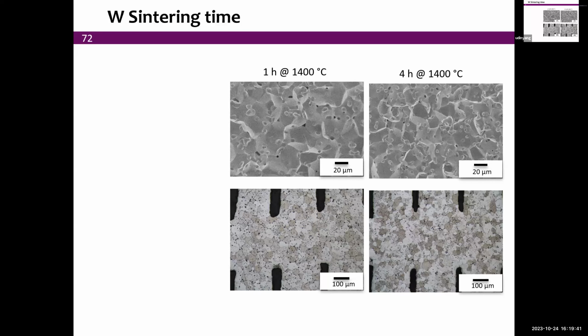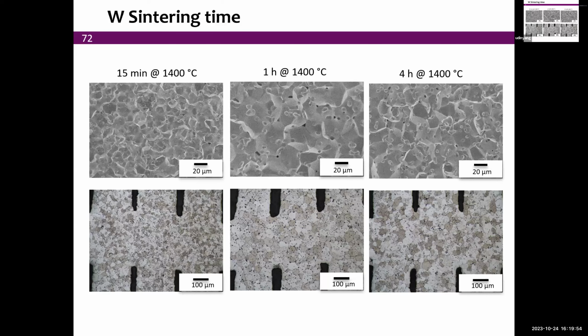We see now for 4 hours, the grains have grown as expected, but it's still pretty fine grains. By the way, this is important: fine grain tungsten has ductility that coarse grain tungsten does not have. And if you go even shorter time, from 1 hour to a quarter of an hour, we have much finer grains, albeit we start seeing some porosity. So we have that control over grain size and therefore the intrinsic ductility of the tungsten.